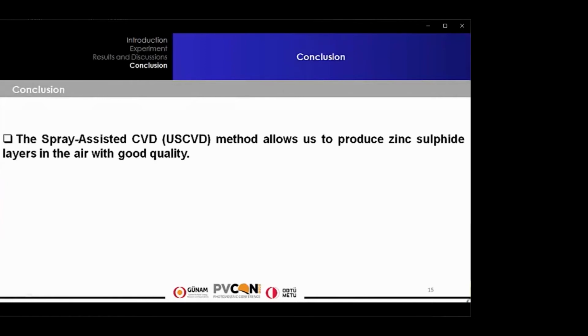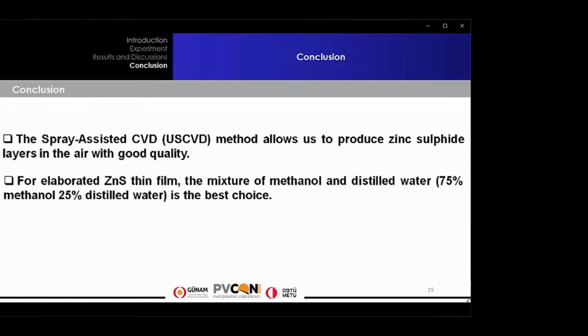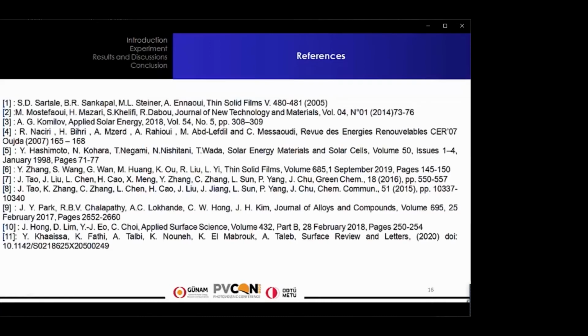Therefore, from the present study we can conclude that the spray-assisted CVD method allows us to produce zinc sulfide layers in the air with good quality. For elaborated ZnS thin film, the mixture of methanol and distilled water, 75% methanol, 25% distilled water, is the best choice. The optimum deposit temperature is 415 degrees Celsius.